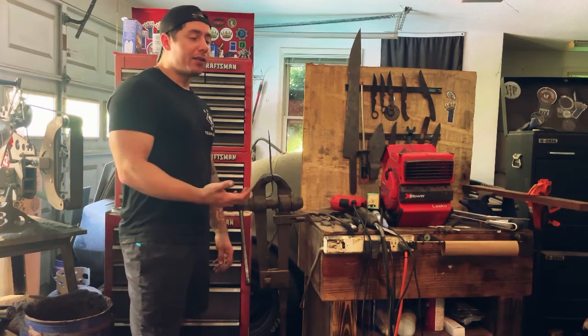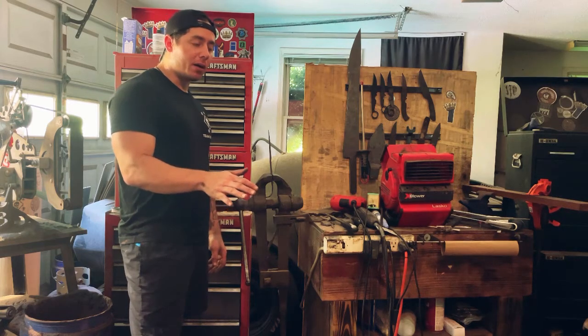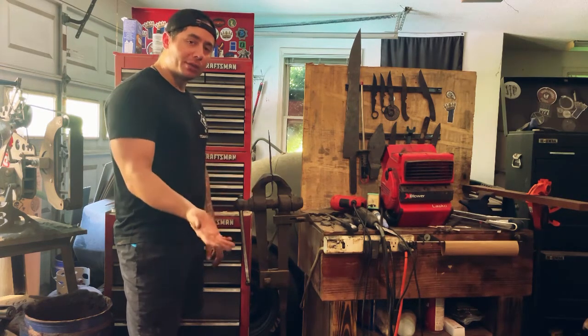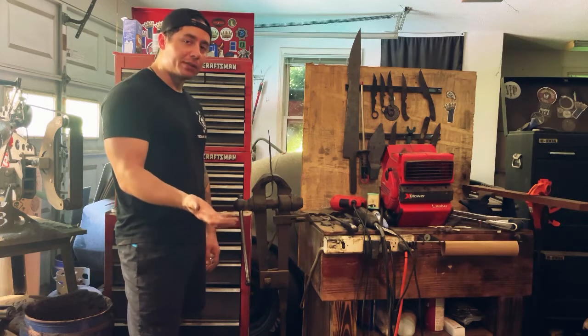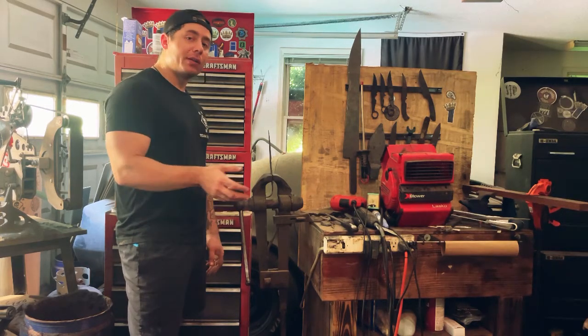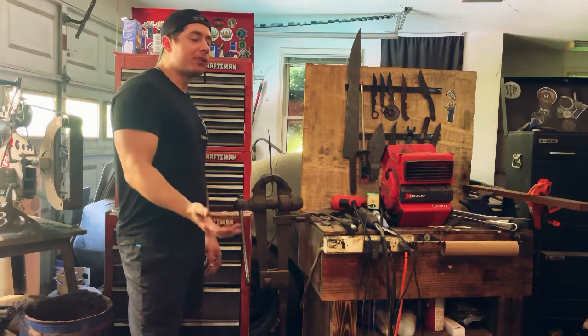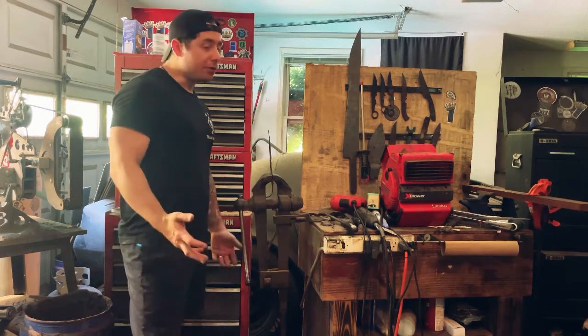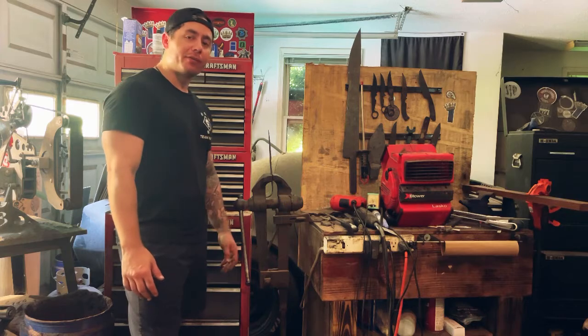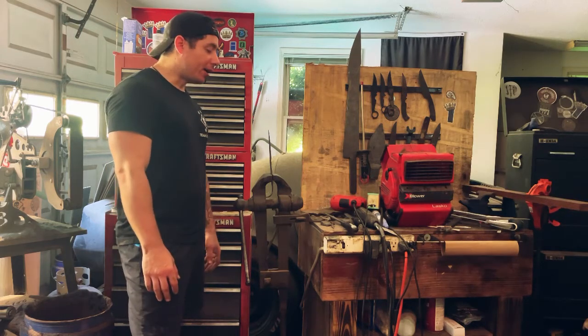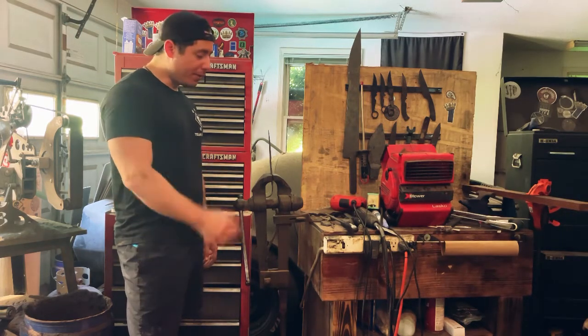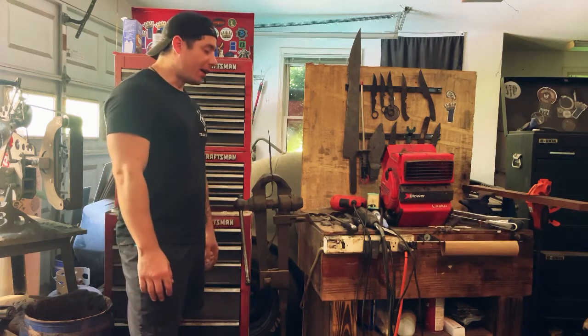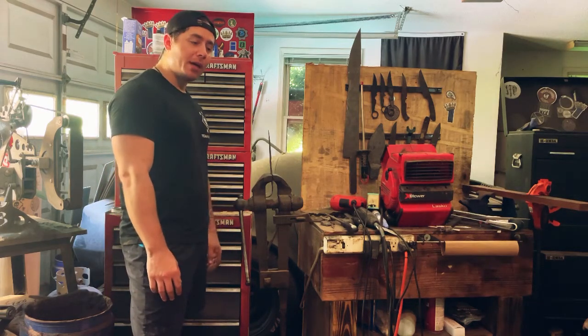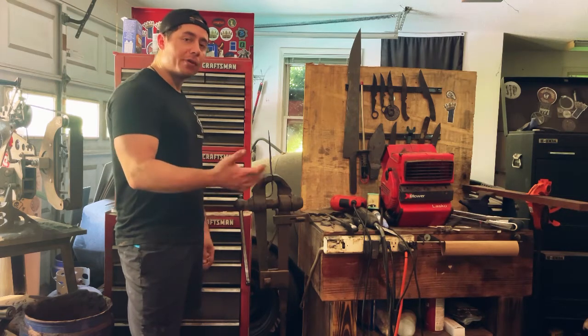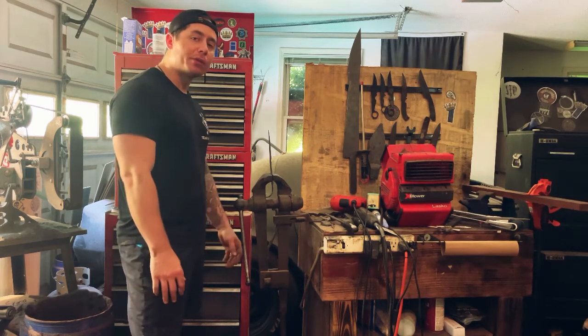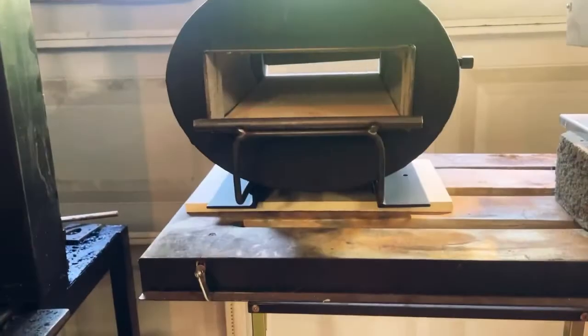And I've noticed a lot of the times when I do that on the anvil, it pulls to the side that's cooling fastest. So actually, my blade ends up warping just from trying to cool it down. You do that 3 times and you have a decent warp. So it took me a little bit to figure out that if I just do it vertically, that doesn't happen. So having it warp at all during normalization is not a thing anymore. So that's why I do that.